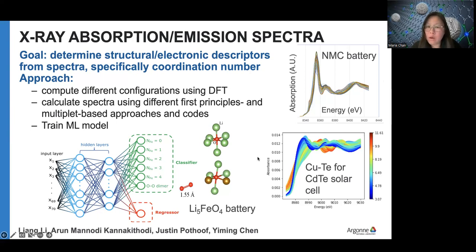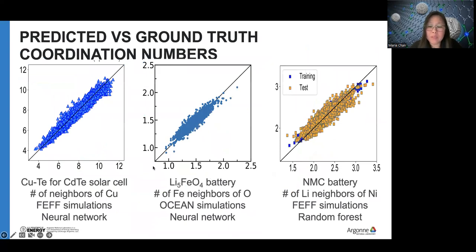In all those cases, we carry out a very similar approach: do a lot of structural configurations using density functional theory, calculate spectra using different codes, and try to figure out which code does the best in matching a few reference spectra. Then we train simple AI models or ML models, such as a multi-layer perceptron or random forest models, and then compare the predicted coordination number to the ground truth, which is what we did in DFT.